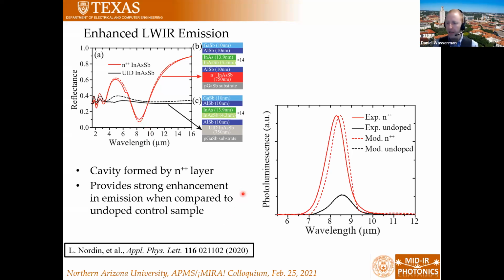Now, if we go and we look at the photoluminescence, namely we optically pump our thin emitter layers, and we look at the photoluminescence, the light that comes from recombination of our pumped electron hole pairs, what we see is a dramatic difference between our control sample and our sample grown on the plasmonic layer. In fact, what you see is about a factor of 7 improvement in your emission efficiency. And you also see your emission pulled a little bit compared to the control. And that's because this cavity is effectively pulling the emission, right?